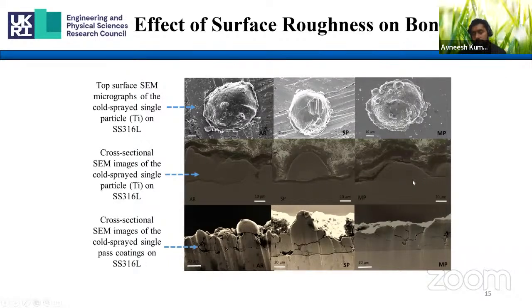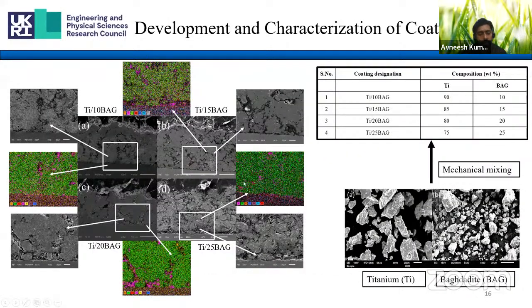However, in the mirror polished case, the contact area was maximum, and the particle was able to deform completely and transfer the energy of the incoming particle to the substrate. This also influences the thermal softening effect, because it is uniformly transferring the heat energy to the substrate. Then we also did some scratch adhesion analysis, which supports the same data, saying that mirror polished substrate surface is good, but because of the time limitation, I have not given the data here. After those results, we realized that mirror polished surfaces are good for bonding.